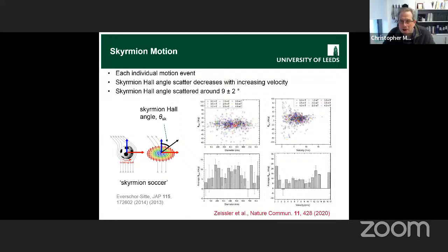What we did find is if we plot against the velocity of the motion. So here again, we've got the Skyrmion Hall angle, and we've got how fast that particular Skyrmion was moving. And you can see mostly they're sort of 5 to 10 meters per second, something like that. There are a few that are moving much faster, and quite a few that were moving a lot slower. And what you can see is, again, there's no particular dependence of the angle on the velocity. It's still an average of about 9 degrees.